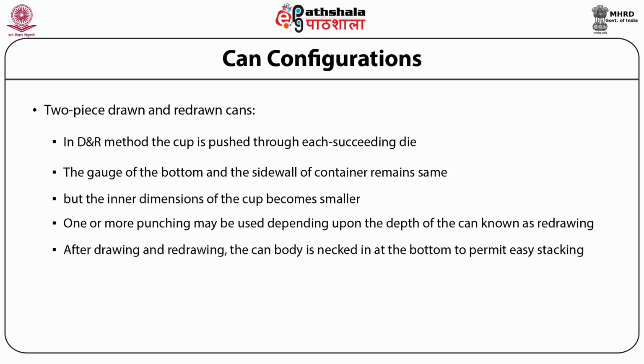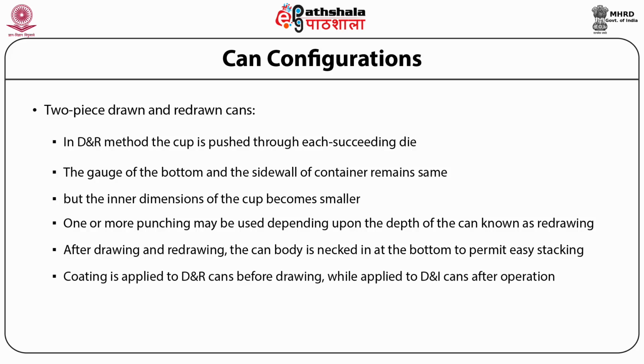After drawing and redrawing, the can body is necked in at the bottom to permit easy stacking and beaded in narrow bands to provide extra side wall strength for vacuum packaging. Coatings will not adhere to D&I cans during production and must be applied after the can body is formed. They may be applied to the flat can stock in the D&R process prior to drawing. A typical can, for example for fruits and vegetables, would start with a 184.6 micrometer gauge and end up with a side wall of 179.5 micrometers. The maximum ratio of height to diameter allowed is about 1.5:1.